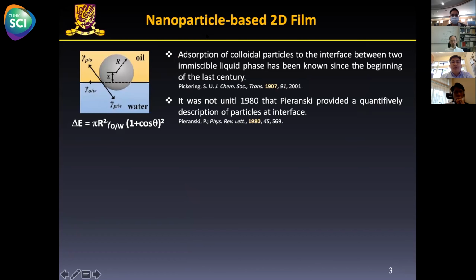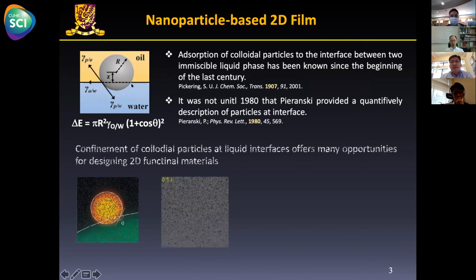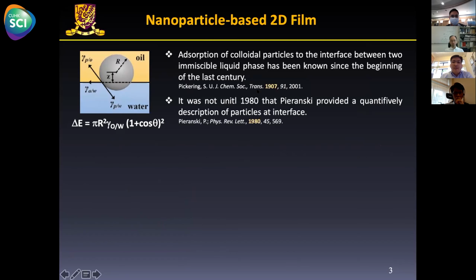The first one, we are looking at nanoparticles when they are trapped at the oil-water interface. This phenomenon has been reported more than 100 years ago, but it was not until 1980 that Pieranski provided a quantitative description of the thermodynamics of the nanoparticle at the interface. That means there are many parameters that can affect this behavior. One thing I want to point out is that when the particle is trapped at the oil-water interface, if you want to detach this particle, the energy is closely related to the size of the nanoparticle.